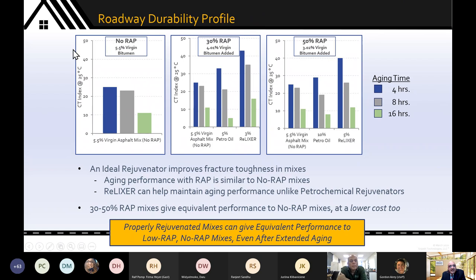Here is Ideal CT data, one of the measures of fracture toughness. We're looking at Ideal CT data. We made a mix with no RAP and 5.5% virgin bitumen. Aged it, loose mix oven aging, 4, 8, 16 hours, measured the CT index, the predictable fall in CT numbers, fracture toughness, as you may expect with aging.